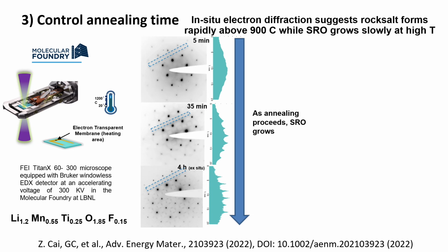Okay. You can also do controlled annealing. We found by doing in situ electron diffraction that when you actually make this material, remarkably, it first makes the fully disordered rock salt, and only over time does it start to introduce short-range order. So what we found is that if we do only very short synthesis times of these materials, we can actually also reduce the short-range order.